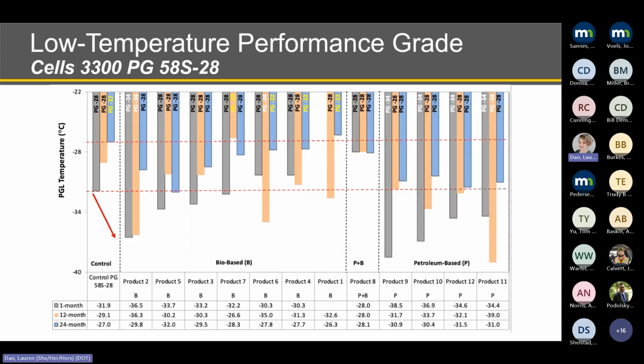For the lower end of the PG, we see similar trends, where we can see a significant softening for some of the products after 1 month of treatment application; as aging progresses, this decrease starts to be minimized. However, we also see for some products, and this is more emphasized for the surface that contains the polymeric material, that some of the products need more time than the short window of 1 month to really give the full response in changing the rheology of the binders.